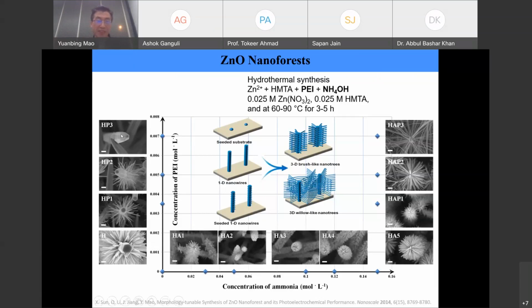Just focus on a couple of things here. You can see that under this condition, the original zinc oxide nanowires changed, especially at the tip. That means something happened in terms of aging, because zinc oxide is not really stable enough under the synthesis conditions we have here. And then you can see sometimes the branches are pretty short, and sometimes the branches are pretty dense, but still short and thick and big.